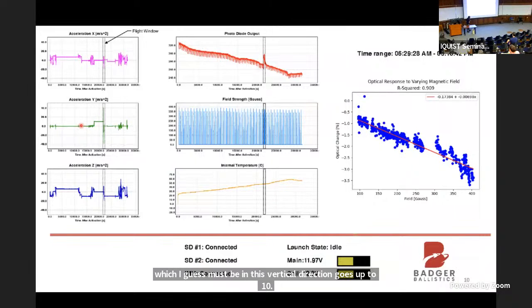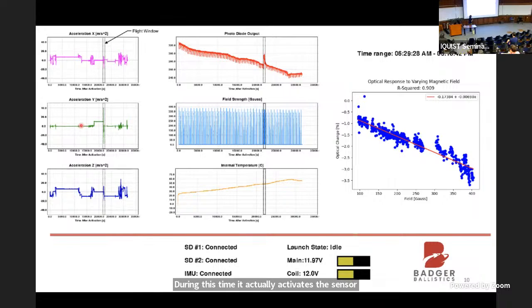And then during this time, it actually activates the sensor to take more data. But what we were doing the whole time is looking at the optical change as a function of the applied field to basically show that you get this nice linearity that's consistent. A couple of other funny things that I guess only matter when you're trying to package sensors. We found a nice temperature dependence of our photodiode signal with the internal temperature, which doesn't really affect the quality of our data because we were doing on and off switching of the magnetic field. So we're able to calibrate basically continuously.